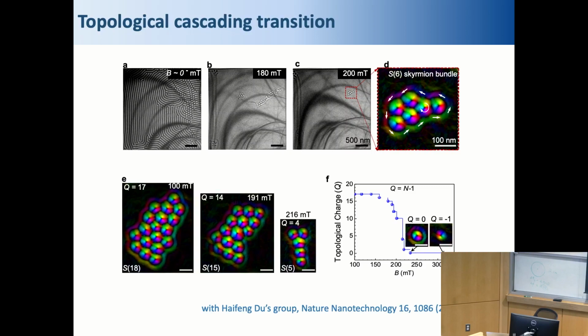This is my collaborators' Lorentz TEM measurement. Lorentz TEM measurement is not continuous, so they take the image every several seconds or minutes. So it's likely that in between 2 measurements, there will be more transitions, and we failed to capture that. But for the same change in field, there's sometimes much larger changes. Yeah. So what determines the strength of the topological protection? When the charge changes, that's when you're violating the protection or overcoming the protection.